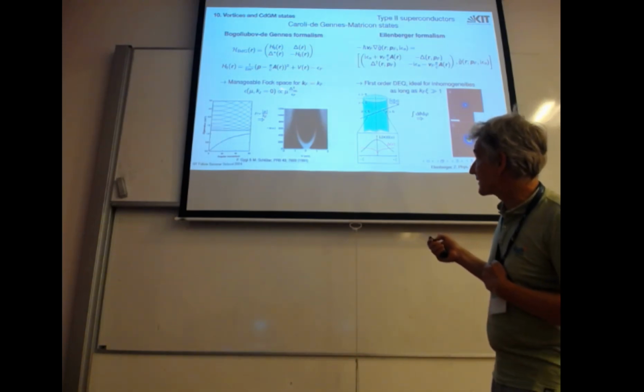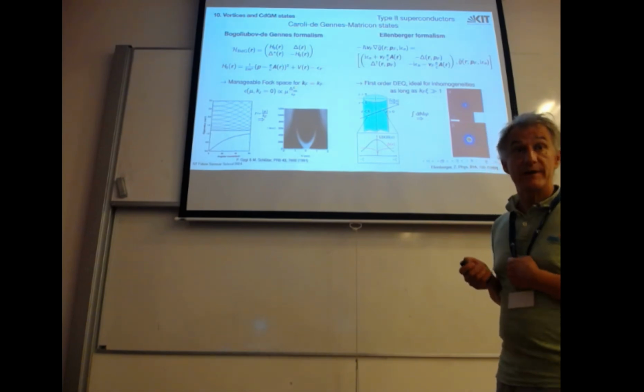The problem is there are really many, many states, because first of all, the z direction is free dispersion, and then the coherence length typically is a big thing. Coherence lengths in superconductors are tens of nanometers, 80 nanometers, 100 nanometers, and the crystal lattice is 0.2 nanometers. So that means a lot of states are involved. The box is big. So actually the level spacing is given by the superconducting gap squared over the Fermi energy. So it's a very narrow level spacing.